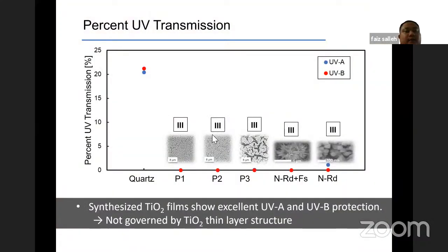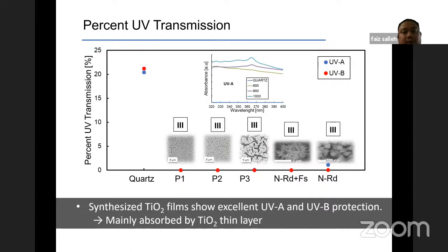If we plot the percent of UV transmission as a function of the sample, we know that all the rutile TiO2 layers have an excellent UV blocking ability. These results show excellent UVA and UVB protection, and it's not governed by the layer structure. When we check the absorbance, we assume that this excellent blocking ability is likely due to the absorbance of the TiO2 material itself.